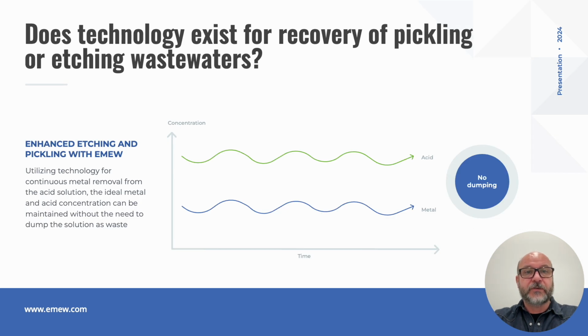Does technology exist for the recovery of pickling or etching wastewaters? And the answer is yes. For spent solutions, technology based on either ion exchange or membranes, this would be diffusion dialysis or electrodialysis technology, these systems can separate the dissolved metal from the acid in the spent solution and allow a significant proportion of the solution to be reused in the pickling or etching process.